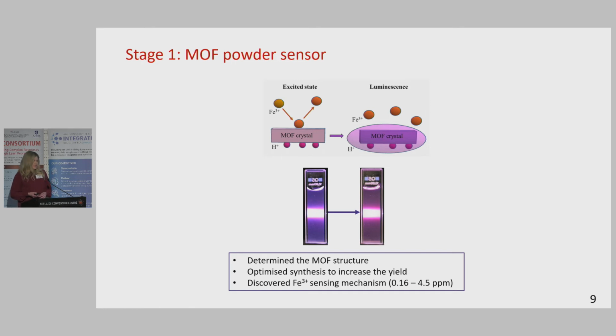So in the first stage, after we selected a potential MOF from the literature, we performed an in-depth study to understand its properties and limitations. We determined new information on the MOF structure that hadn't been published before. We optimized the synthesis to increase the yield from 4% to 32%, and we also looked into why we have a response from the MOF crystal to the presence of ferric ions. Why do we see the change in the emitted color and the intensity of the light?